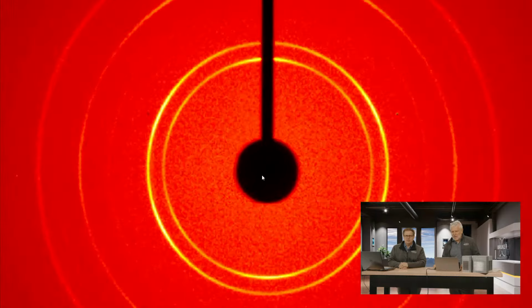So the point here is that you don't see anything. I don't even see any counts. Sometimes you'll get a gamma ray, or cosmic radiation in there. We didn't talk about this at all, but we also have high energy event discrimination on that detector. But here the point is, we took a contrast image. It's a foil that has a lot of amorphous scatter, actually more than amorphous scatter. You saw some texture there. So we create a pretty strong flood field, 60 seconds, but we don't have any counts behind the beam stop. People use this as the proof of the pudding, whether you have low noise. And how long was this collected? That's 60 seconds. Really? Yep.